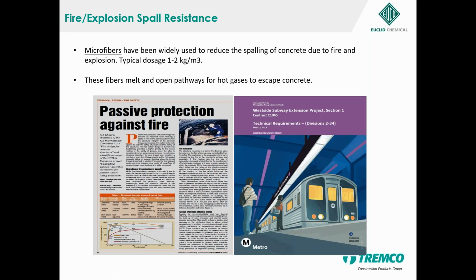You have to understand passive protection against fire. These microfibers have been used in transport tunnels, in case there is a fire and smoke. These particular fibers burn at around 165 degrees, and micropores are created in the concrete, which allow the bad smoke to go out so that people do not inhale it and die. That is one of the reasons hot gases and other things escape out from there. This is what is happening in some of the specifications which are coming out of late.